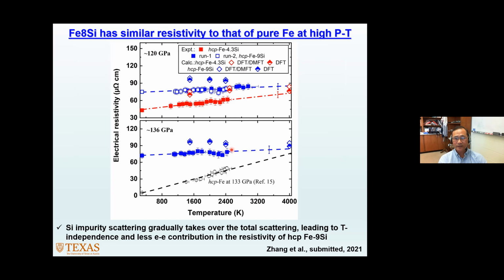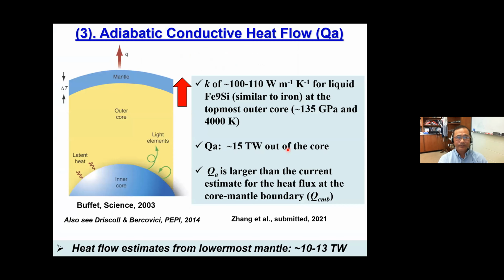gradually takes over the total scattering that we talk about, especially at high temperatures. And if we now take a temperature of about 4,000 Kelvin at 136 GPa, that's the pressure at the topmost outer core, then the electrical resistivity of iron-silicon alloy is very similar to that of pure iron. Okay, so I think this is one more unexpected result that we found in this study here.